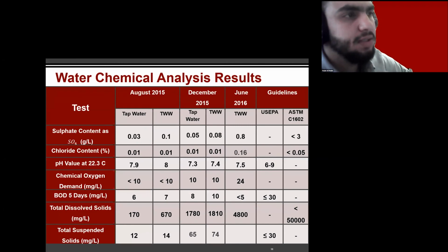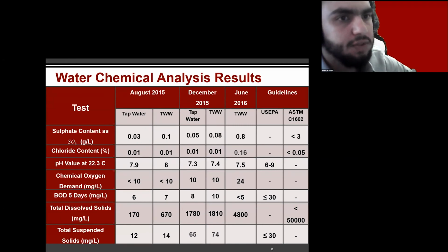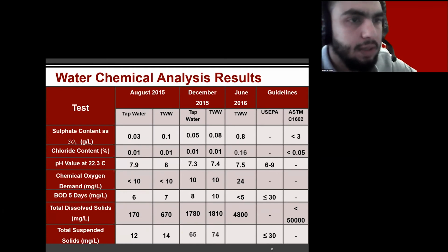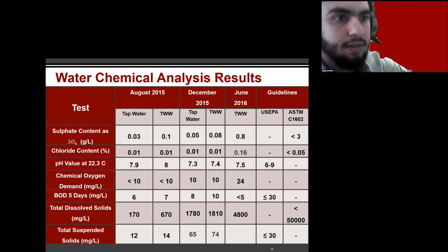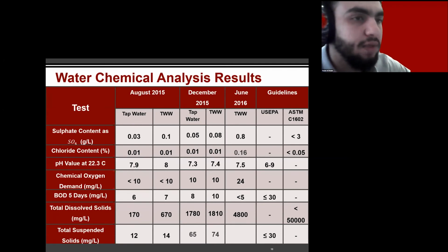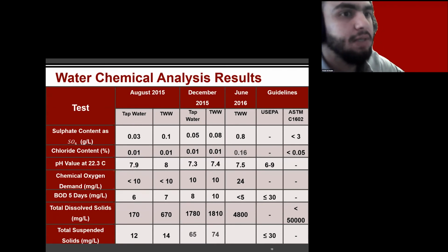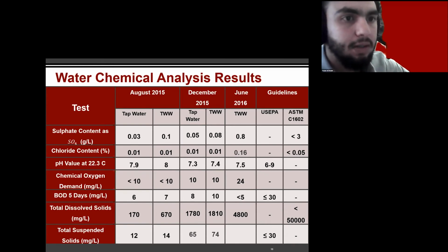Prior to the study, 3 samples of water were taken from the source over a period of 1 year to test and ensure that the quality of the water is within the acceptable limits set by the USEPA and ASTM guidelines. This table summarizes the results, and as you can see, almost all values fall within the acceptable range.